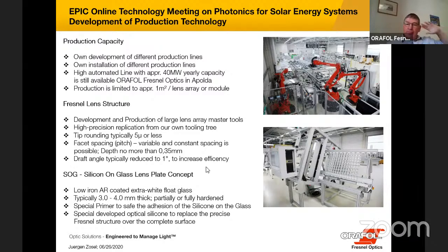reduce, for example, the draft of our Fresnel lens, because a draft of a Fresnel lens is regular in the range of about 3 degrees. Just to produce these lenses, or to be able to produce the tooling tree, we did spend a lot of time and development to reduce this draft, for example, from 3 degrees to 1 degree, just to increase the efficiency of the module.